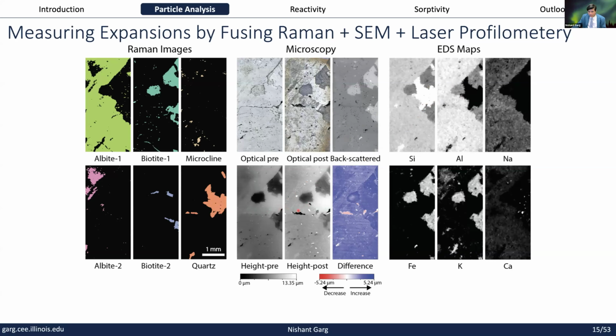And then if you look at the pre and the post map, you can see in the post map it's now glowing, which means its height has increased, which means the quartz has basically expanded. And due to that expansion, some of that quartz has even broken out of the sample. By fusing multiple techniques, you can get phase-specific expansion as opposed to an average expansion. Now you know which phases are expanding.